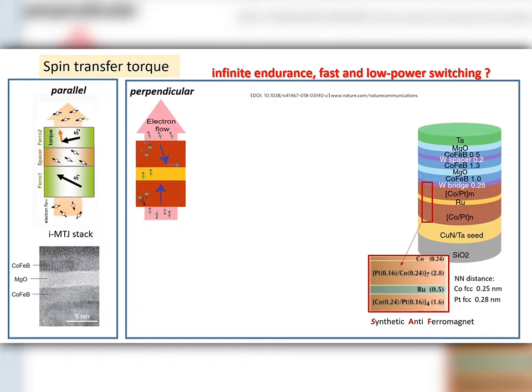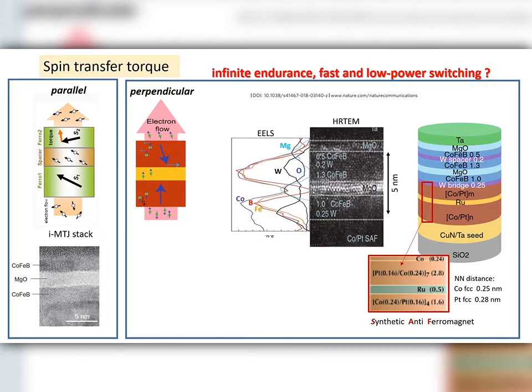Normally we have here the MRAM element consisting of 13 elements, and you see here relatively thin CoFeB layers adjacent to a synthetic antiferromagnet. There are in some publications element distribution measurements presented, and you see here one example where you can realize that you have at the interfaces, or there are really no interfaces, you have a strong intermixing of the elements.